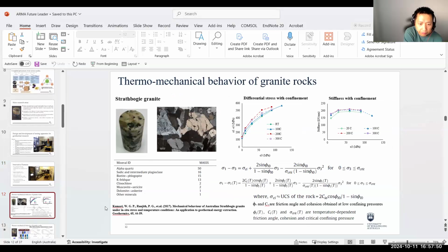So basically you heat the whole setup to 300 degrees C, and also increase the confining pressure to, for example, 50 or 100 MPa, and then you start to compress and break the rock. Yes, that's correct.